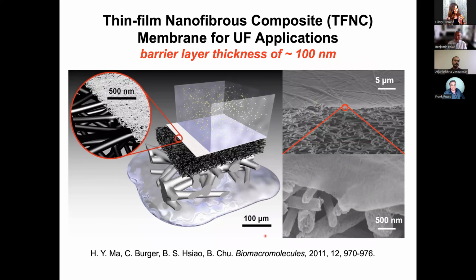And for an ultrafiltration membrane, the typical smallest pore size will probably be less than about 10 nanometers or so. For the electrospun scaffold, we're not able to accomplish that. So this is where we started with the nanocellulose process. Nanocellulose is nanofibers made of any biomass that we can extract. The fiber diameter is in the range of maybe 5 nanometers or so. If you remember my 3-to-1 rule, that means the pore size will be about 15 to 20 nanometers. And that's probably a very good range for an ultrafiltration membrane, which we actually made into a system like this.